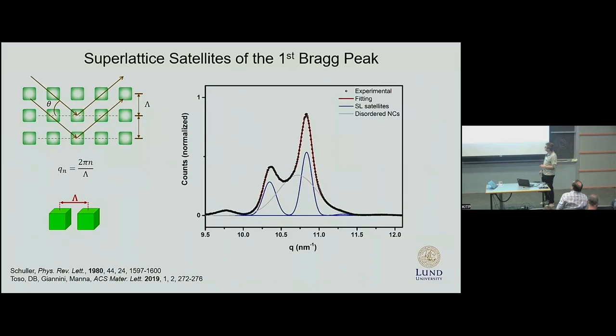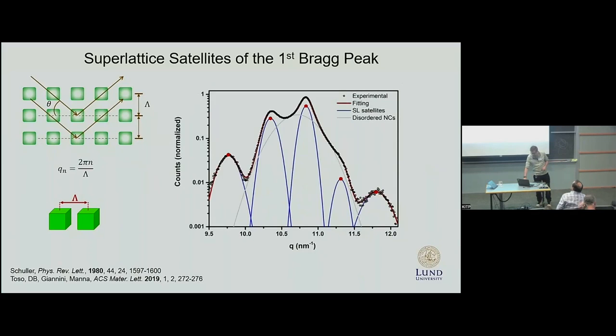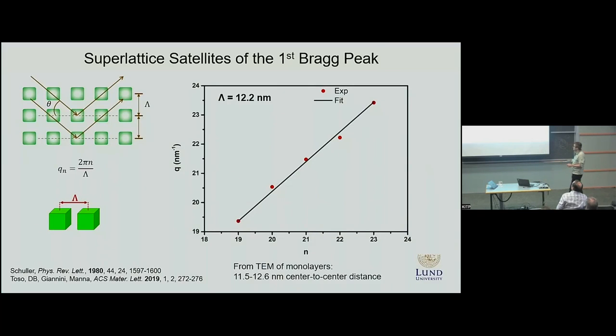First we could do some phenomenological analysis and simply fit the diffraction peaks following a rearranged Bragg's law. So we replot this diffraction peak on a logarithmic scale, fit it as a sum of contributions from disordered nanocrystals and then these multilayer reflections, fit it following Bragg's law, and then we can extract lambda, which is in this case the superlattice constant or center-to-center nanocrystal periodicity, which agreed fairly well with the center-to-center distance measured in TEM on the nanocrystal monolayers.